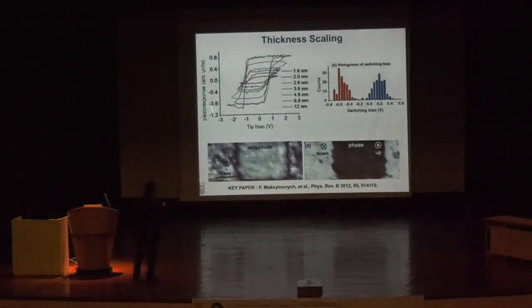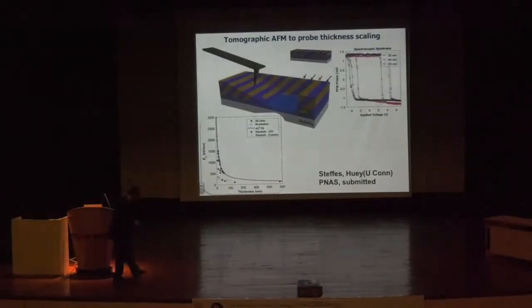Okay. You could also see some signatures of why the coercive field is not dropping as 1 over T. It's sublinear. Over the last year or so, we've been working with some folks at Connecticut. Brian Huey is a faculty member there, where you can take an atomic force microscope, and it's very much like shaving with the atomic force microscope. You cut one layer after the other, and this is called tomographic AFM. So you can take a 100 nanometer thick sample, and you can progressively reduce the thickness and measure the ferroelectric properties. That's what Brian did.